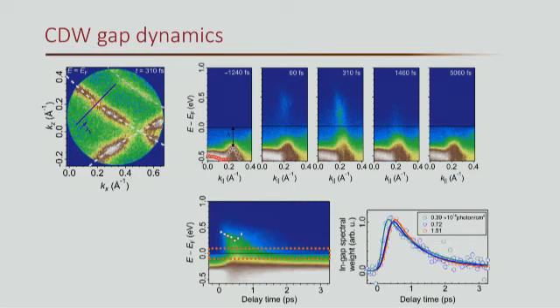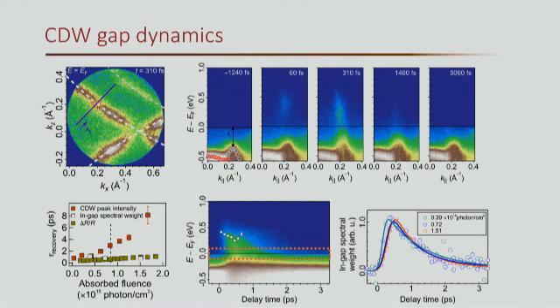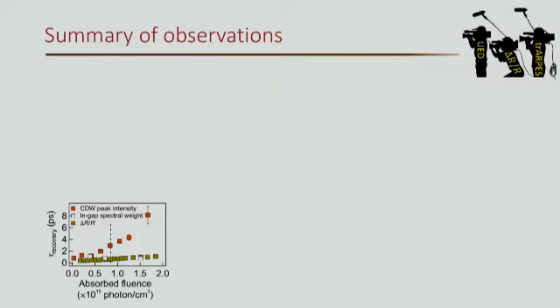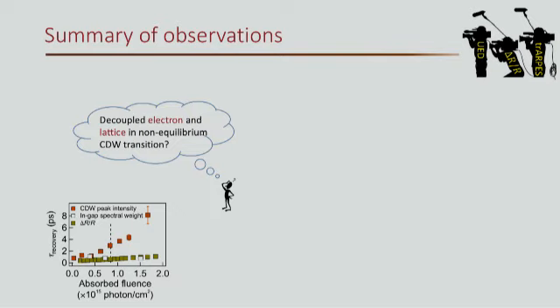And here's the result. We did two other fluences, and we combined the three ARPES points into our previous plot. You have seen the red curve and green curve before, and the three white squares are the ARPES timescales, which agree pretty well with the electronic relaxation time seen in delta R over R. Aha, so now you think, ARPES and transient reflectivity show the same timescale. So it must be that electron and phonon are decoupled during the recovery process, because in ultrafast electron diffraction you are probing the lattice recovery, while in ARPES and transient reflectivity you are probing the electron recovery. But is it really the case? We thought about it for a long time, but eventually came to the conclusion that this couldn't be the case.